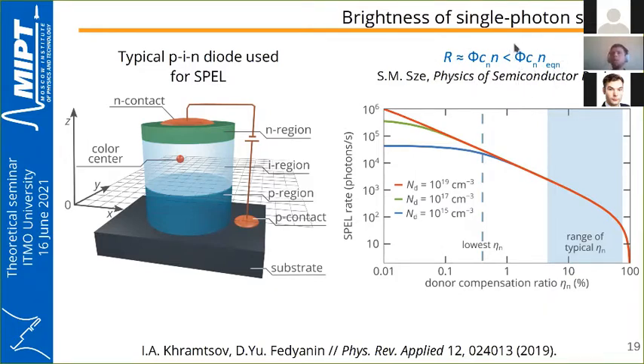If we now plot phi times Cn times n in equilibrium as a function of the donor compensation ratio, we can see that for the range of typical compensation ratios, the single-photon electroluminescence rate will be no more than 1,000 photons per second, which is very low for practical application.